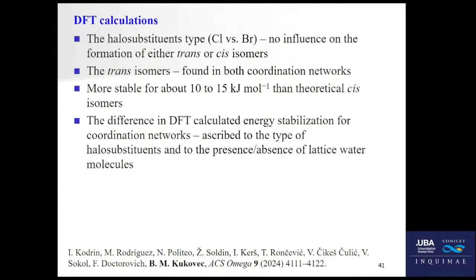So for now we did some DFT calculations, but only at this point on chloro and bromonicotinate polymers, and with the help of these DFT calculations we concluded that the halogen substituent type, be it chloride or bromide, had no influence on the formation of either trans or cis isomers around palladium. So in all cases we got the trans isomers, and the theoretical trans isomers are 10 to 15 kilojoules per mole more stable than cis isomers. So this DFT result was in accordance with the structural result.